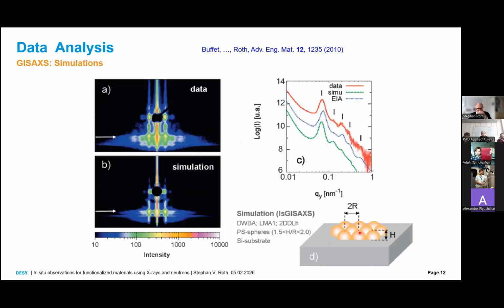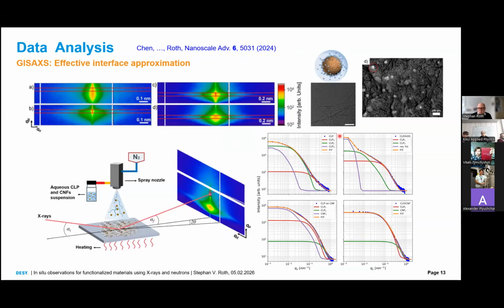Yeah, this is, so to say, the nice scattering pattern. Typically, scattering patterns look like this. They look more featureless because other examples like cellulose or other wood-based materials give a more disordered structure. You see here the typical scattering patterns, and here again the one-dimensional cuts. Then we have to apply a more advanced modeling where we include a resolution function on our sample, and we include our different components as form factors. By incoherently adding all the three components of the different structures, structure factor times form factor, we can quite well reproduce the curve, and we find these structures in the experimental data. So this shows you the method of grazing incidence, that we can really go from the molecular level to the nanoscale or mesoscale level in full detail with all structures, and we are able to quantify all structures present.